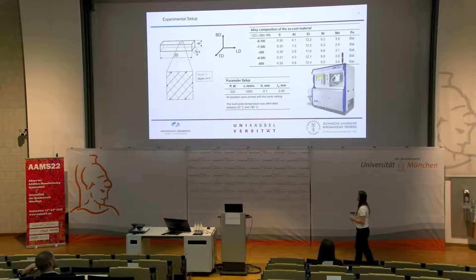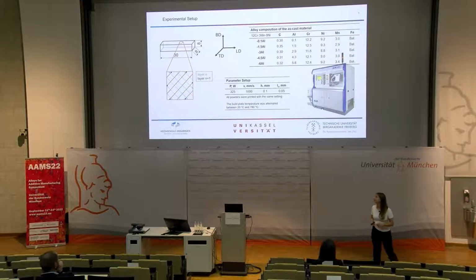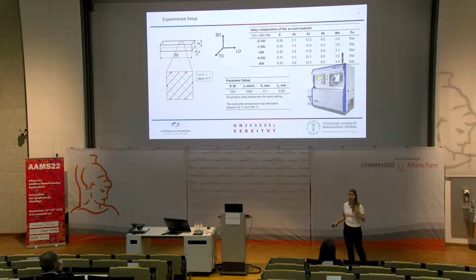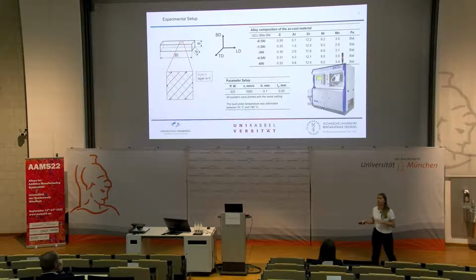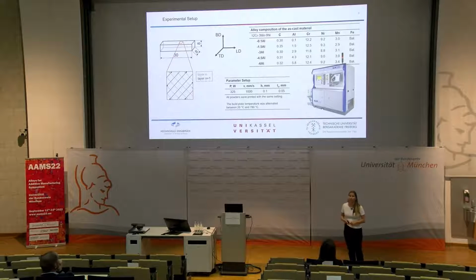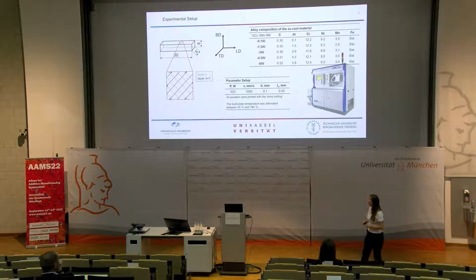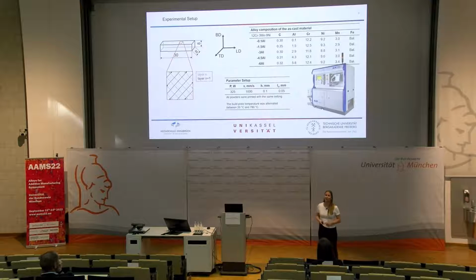The experimental setup we used for this was an SLM280HL machine, and all those compositions I already explained were printed with the same parameter setup. Due to a limited amount of powder, unfortunately we were only able to print in a lying-down position, so the building direction is perpendicular to our loading direction in the present case. The process condition we were changing was the temperature. As we all know, the temperature of the build plate is crucial for our solidification rate, and the SLM280 is able to heat the build plate up to nearly 800 degrees. Due to safety reasons, it will shut down at 800 degrees, therefore we used 780 degrees.